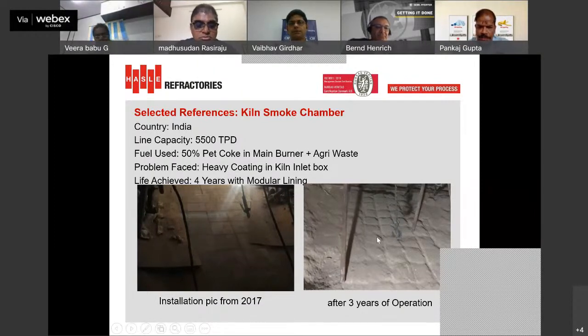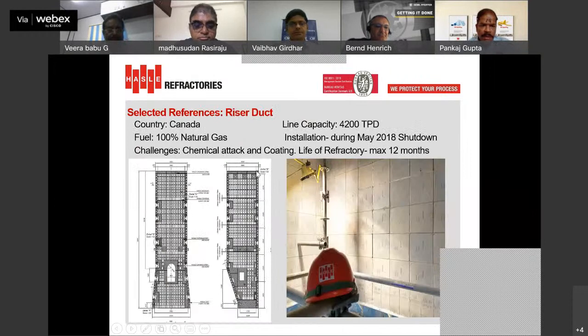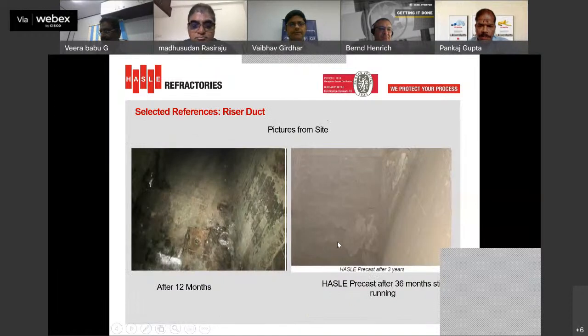This picture after 3 years. This is a plant from Canada which is using 100% natural gas, but actually because of this natural gas, they are facing a lot of chemical attack and coating issue in their riser, and getting a life of maximum 12 months in their riser area. So we replaced it in 2018. The whole riser was replaced with the precast lining, and now it has already crossed 3 years. This is a picture after 3 years, and still it is very compact, and we are still expecting 2 more years of life with this lining.